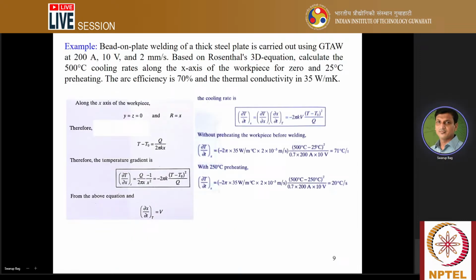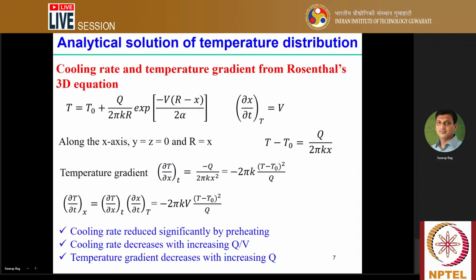And from the application, we can see that del X by del T is equal to V, the velocity. Now the cooling rate, del T by del T, at one particular fixed space, is equivalent to del T by del X into del X by del T. And we can see that this is equivalent to 2 pi k V (T minus T0) squared by Q. We have already seen that part here. The cooling rate we can calculate as 2 pi k V (T minus T0) squared by Q.